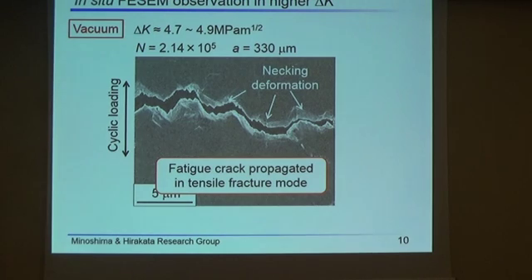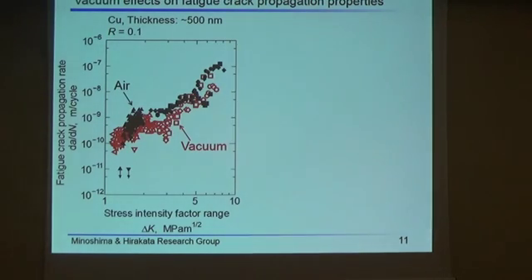Fatigue cracks in air also propagated in tensile fracture modes. So this result obtained in vacuum is consistent with that in air. On the basis of these experimental results, vacuum effects on the fatigue crack propagation properties were investigated.